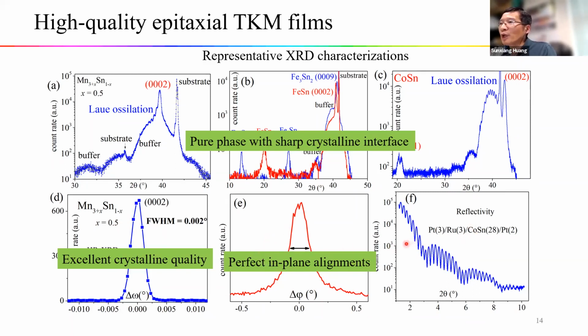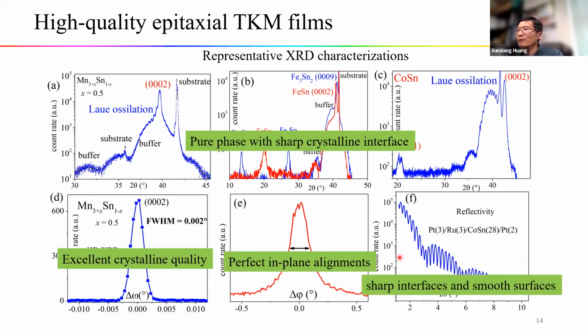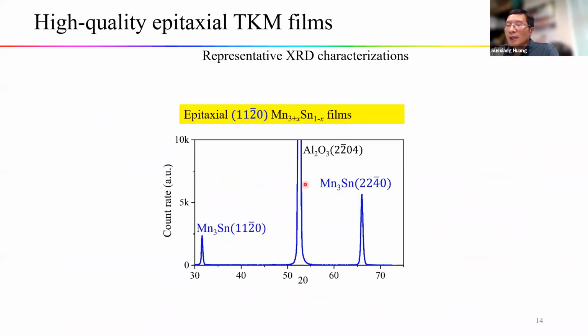The reflectivity measurement shows oscillation peaks from low angle to about 10 degrees. So this shows the film has sharp interfaces and a smooth surface. We also made some of these manganese-tin films as shown here. The XRD shows only one or two peaks without other orientations.